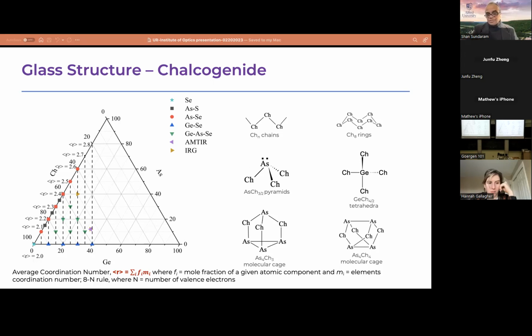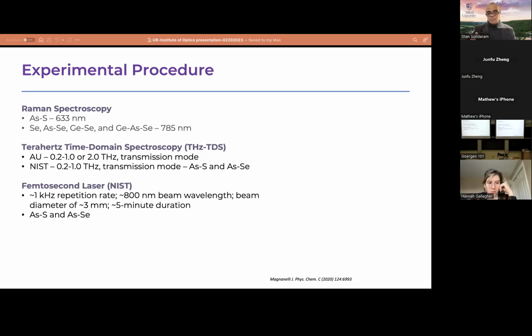So I just showed you all these things. Once again, we used Raman spectroscopy to look at structural features of the chalcogenide glasses. We used terahertz time domain spectroscopy, which we measured in our lab. Then we also measured selected glasses at NIST, in a very similar frequency range. We also used a femtosecond laser system that NIST has, with a 1 kilohertz repetition rate, 800 nanometer beam wavelength, and a beam diameter of 3 millimeters, and we irradiated these glasses for a 5-minute duration. This is some of the things we did, but I want to show you what really happened to the terahertz properties.